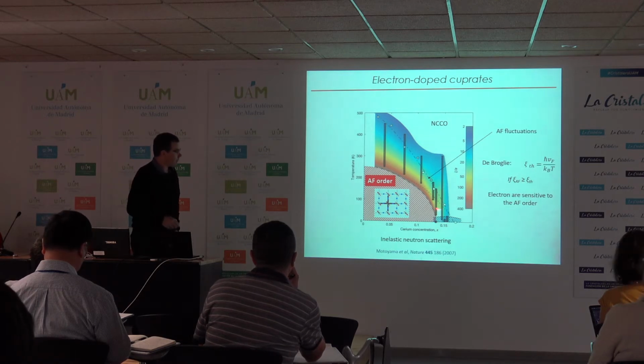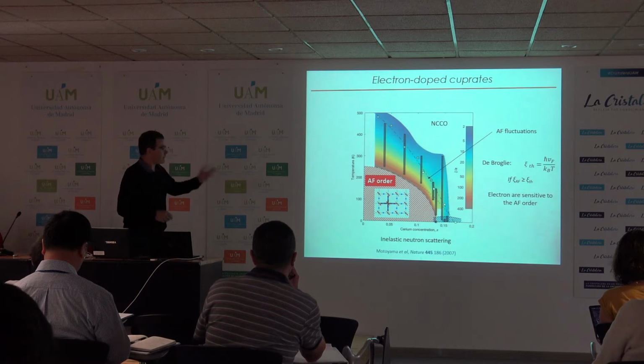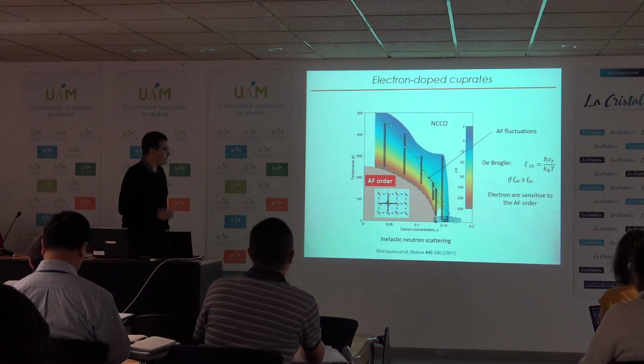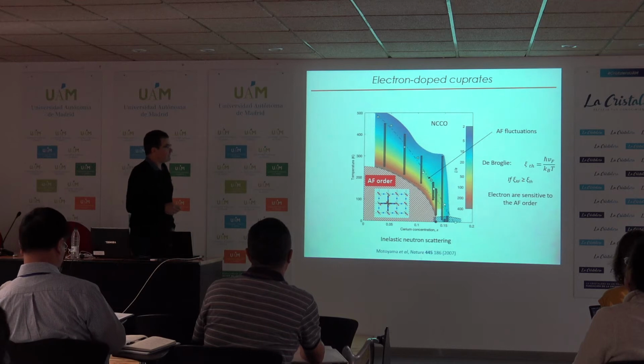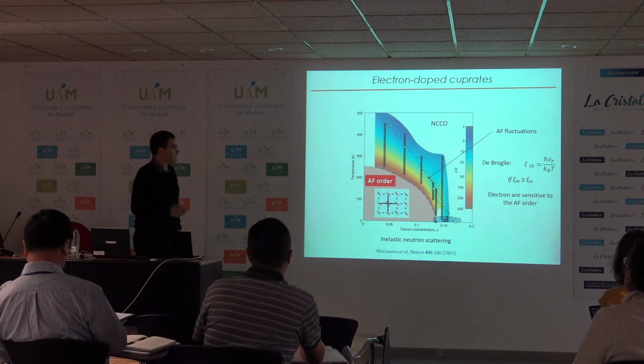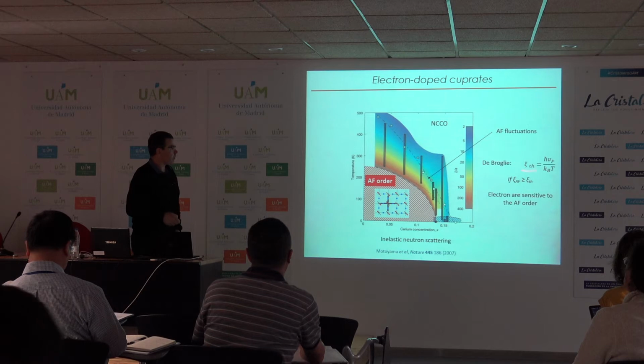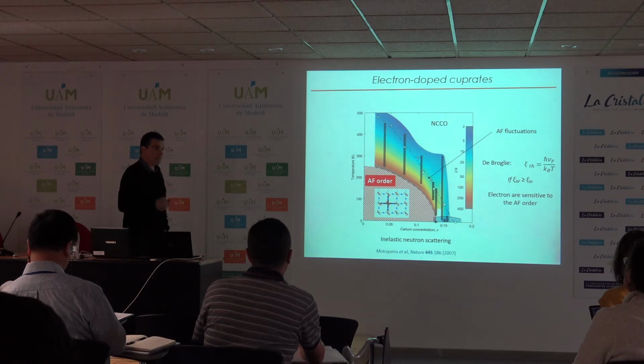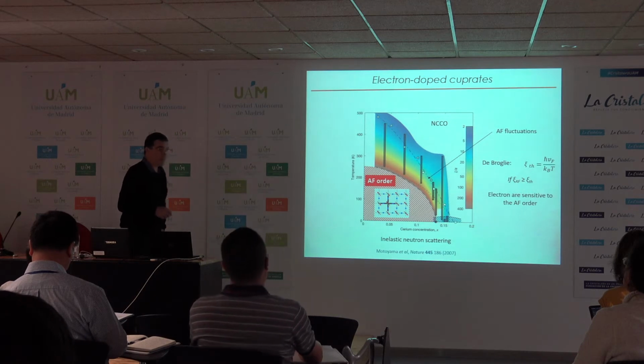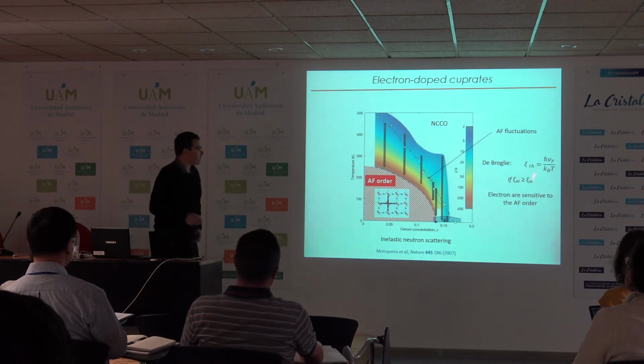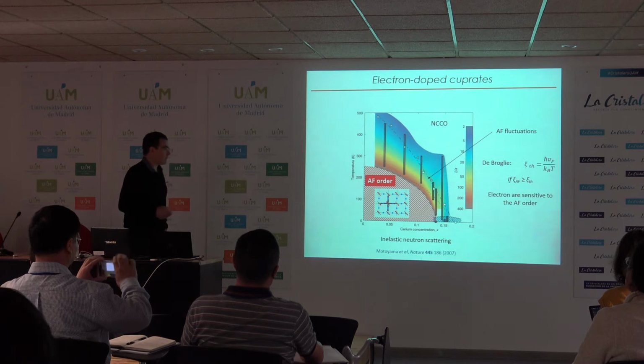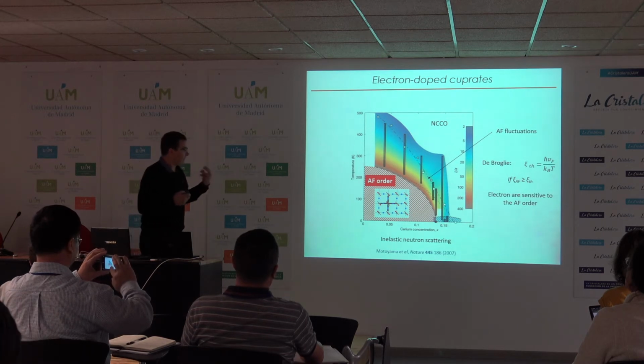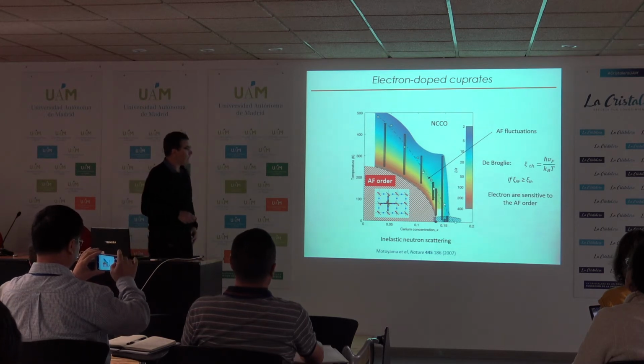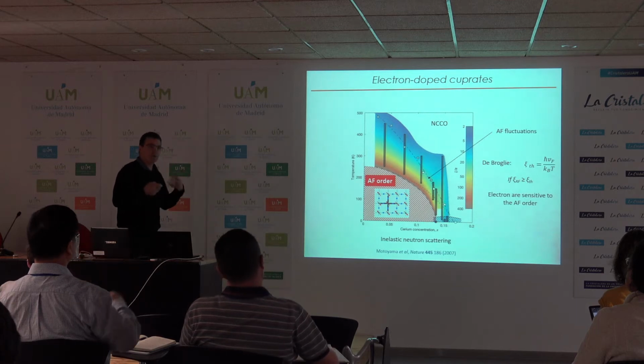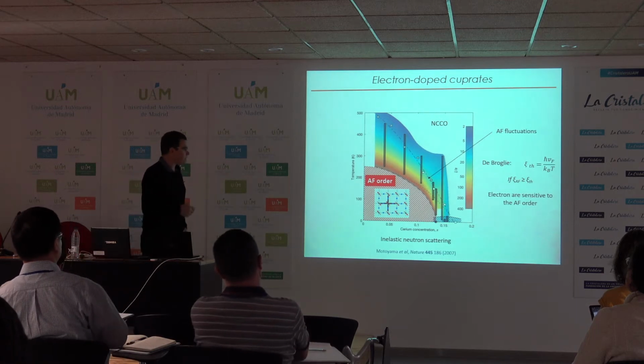The orange color corresponds to a long distance antiferromagnetic fluctuation. And if you compare this antiferromagnetic fluctuation coherence length to the de Broglie correlation length of the electron, you can notice that the antiferromagnetic correlation length is much longer than the de Broglie correlation length, meaning that in fact, even in this state, the electrons are still sensitive to antiferromagnetic fluctuation.